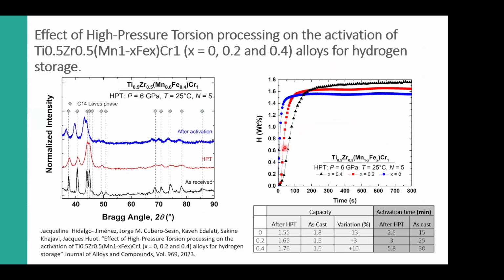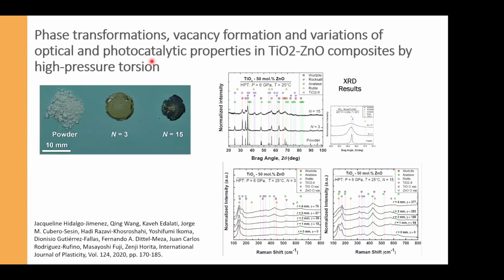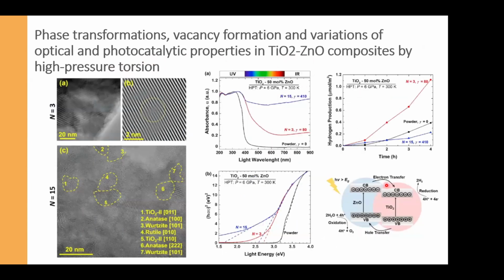There's research in hydrogen storage, as I said. So this is a complex intermetallic phase. We can refine them with HPT and get, for example, higher kinetics in hydrogen absorption. And we are doing some of this work. We did a little bit earlier work with titanium oxide. We can synthesize it, as you see here. And for example, these kinds of oxides are interesting for photocatalytic conversion, for example, turning light into energy.